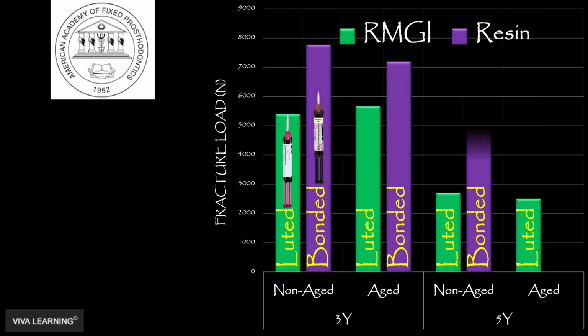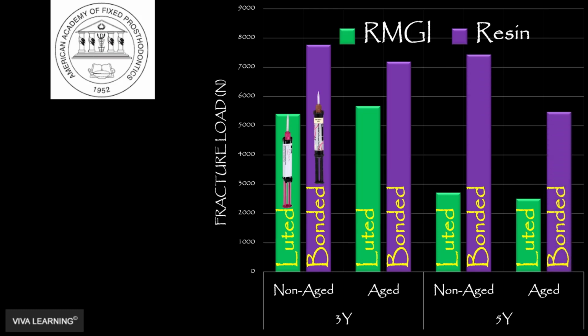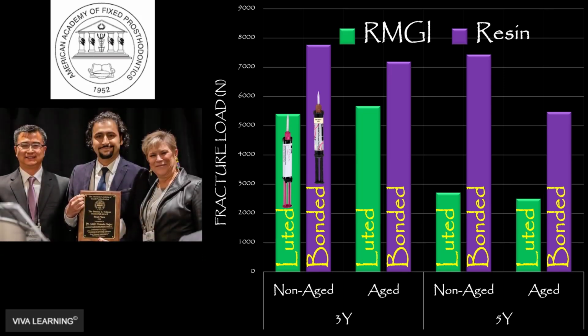We did a study that was funded by American Academy of Fixed Prosthodontics, and in that study we found that when the restorations, whether they're 3Y or 5Y, when they were bonded, they became much stronger than when they were just luted with resin modified glass ionomer. And actually that paper won the first place in Tylman Award. And I can say that really proved to me that bonding in place a ceramic restoration can have a significant effect on increasing the fracture resistance of the restoration.